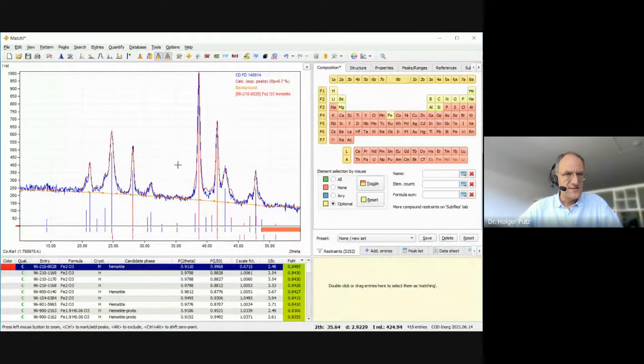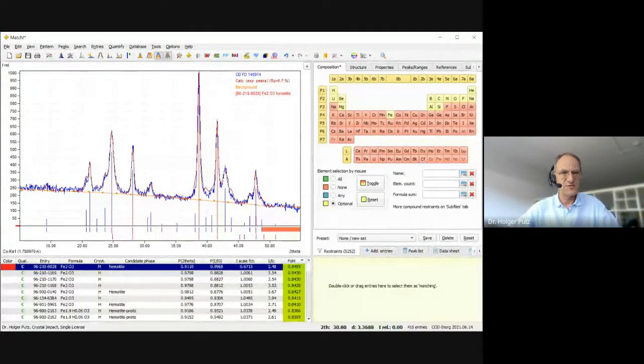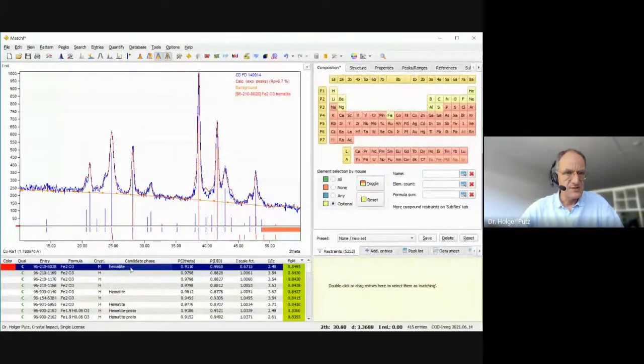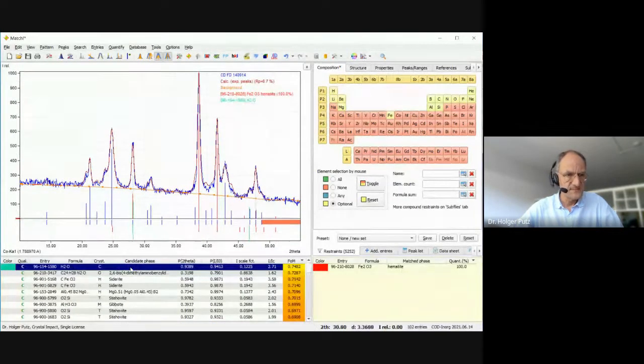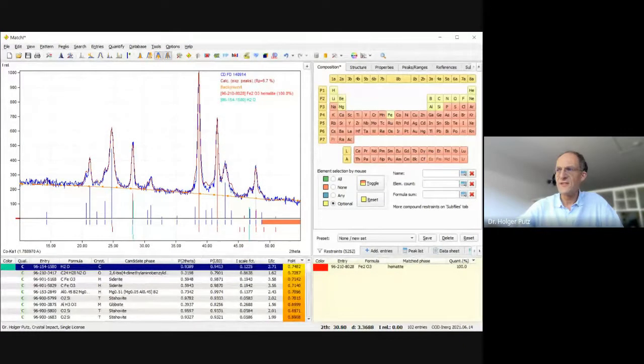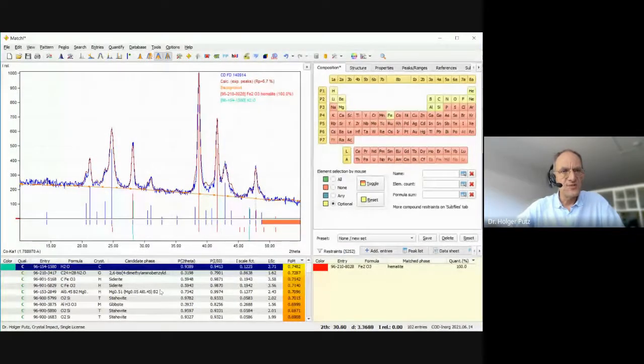Okay, this is the first or best matching phase, hematite, which is not really so surprising if you have iron ore. And I will double click it to select it. And now there's quite a list of other phases, but it's not so clear which one of these is really present in the diffraction pattern or not. So I will use a different approach now for selecting phases, and that is to focus on peaks that have not been covered by identified phases up to now.